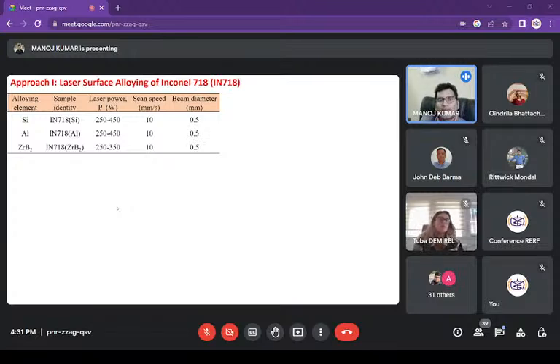One is from laser surface alloying. We tried to alloy the surface of Inconel 718 with silicon, aluminum, and ZrB2. Inconel 718 consists of nickel, iron, and chromium. So when we melt with silicon, it will form nickel silicide, iron silicide, and chromium silicides, right? These nickel silicides and other silicides are intermetallics with high melting points and stable at elevated temperatures. The same thing will happen with aluminum. If you alloy with aluminum, it will form aluminides.